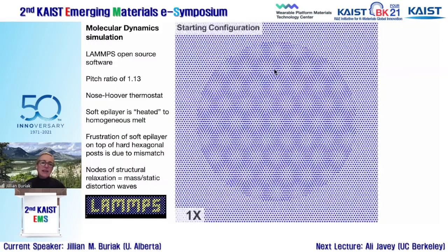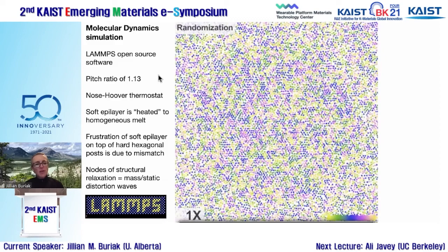And so what Brian did is that underneath here, I'm going to then go and heat this, okay, to give you a homogeneous melt. But underneath we have a hard hexagonal post system that's been modeled. And we're going to put a soft, mushy polymer over top, and we're going to see what happens. Okay, so in this model, we've melted the epi layer. Okay, so it's a homogeneous melt using a Nosé-Hoover thermostat.